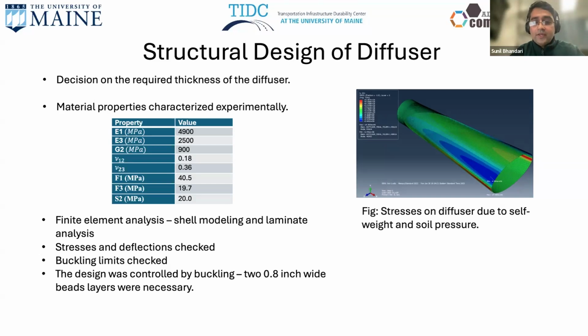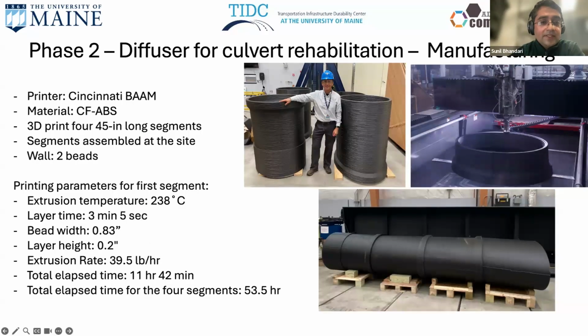So if we wanted the buckling ratio to be higher because the material properties are expected to deteriorate over time, we had to go with 0.8-inch wide bead layers. So we designed the joints and we manufactured the culverts using the BAAM printer here at the Composite Center. We used carbon fiber ABS material because it's more durable and it was deemed suitable for a longer lasting structure.